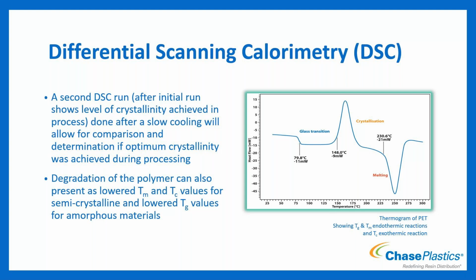We're going to have issues with stuff like our wear performance or our heat performance, chemical resistance performance. And so if we're having a material or a part that's failing with something like that, that under circumstances you would think would be reasonable to expect that material to perform like that, we could do a DSC to determine if we're meeting the optimal amount of crystallinity we should be, or if we're going through it too quickly and not allowing it to crystallize fully. So it is a good test to be able to do that.